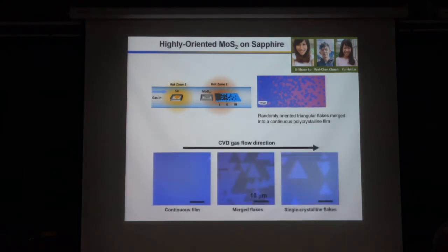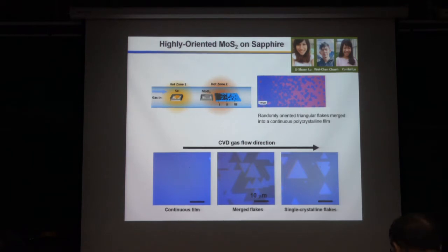But if you carefully control the growth condition, you can use the sapphire surface lattice to guide the growth. So you can see it's upstream, midstream, and downstream. So you can see these grains, they have the same orientation or the opposite, but they are not random. So in this way, when they stitch together, they will form a continuous film. That still has some grain boundary, like this mirror twin boundary. So actually they still have some grain boundary. But in this case, the film quality is much better than this kind of randomly oriented grains forming a continuous film.